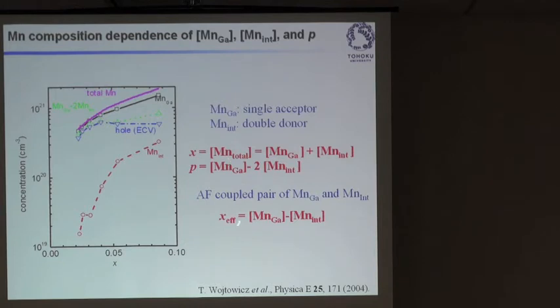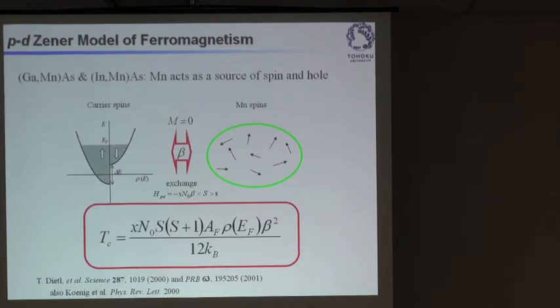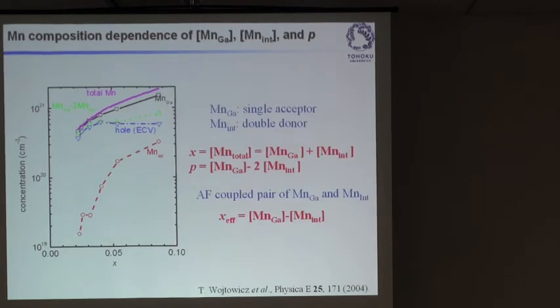And the slide here on the left-hand panel is where these authors compared this number, determined independently, with the hole concentration. They independently determined these two numbers and plotted them here, and they showed that indeed the measured hole concentration is closely followed by this equation, which means that at least this equation here is correct. Okay. So now we know how many manganese we are having in our system, how many holes we have in the system, and how things are compensated in the system.